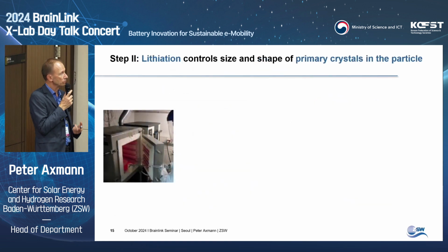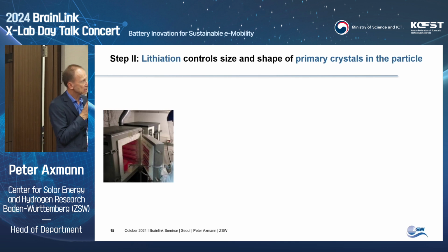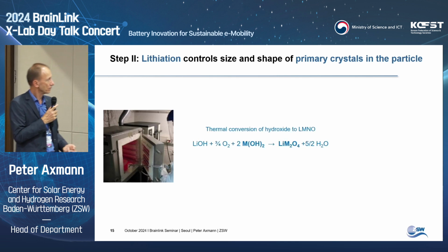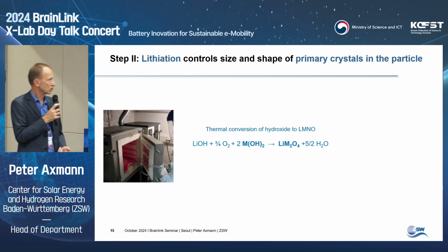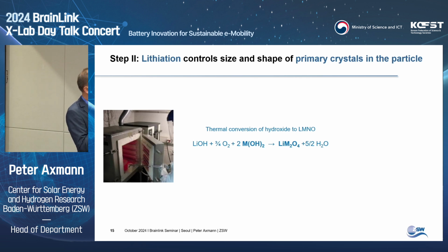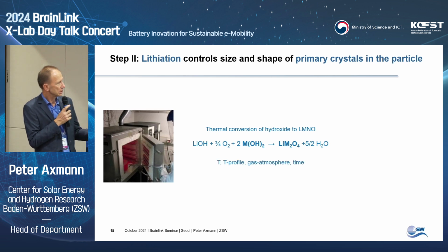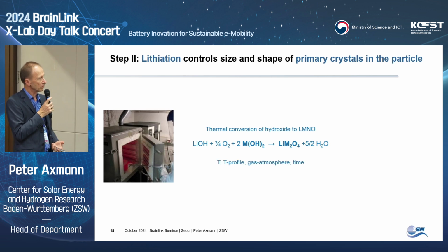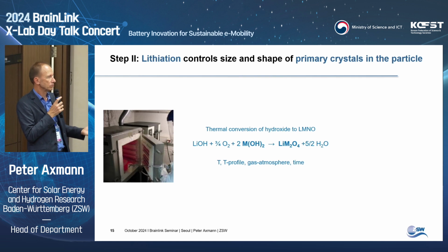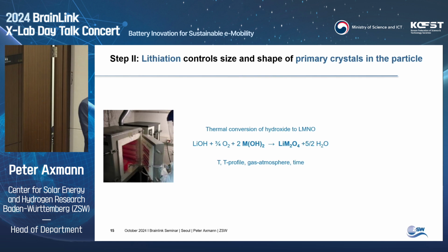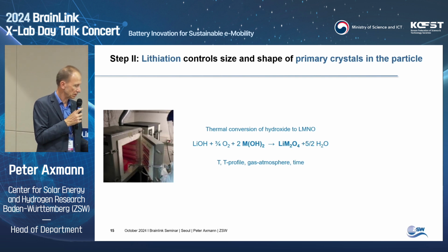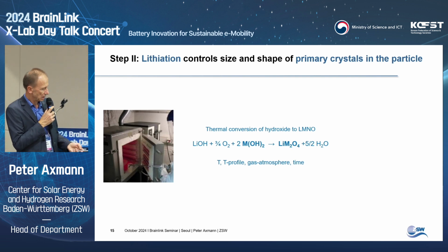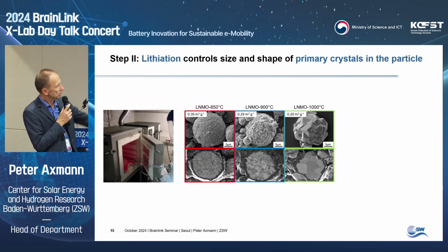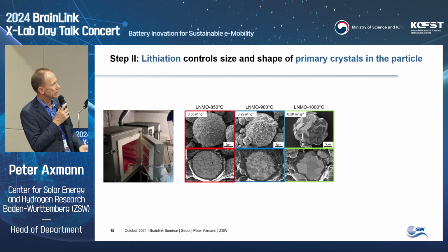Step 2, the lithiation. Here we can control size and shape of the primary crystals within these individual particles. The reaction is a thermal conversion of the hydroxide to the final product, here as well, LMNO. You put lithium hydroxide to it, oxygen, the hydroxide, and end up with a final cathode active material at 700 to 800 degrees. You can change the temperature here, temperature profile, gas atmosphere, and time of exposure. And just changing the temperature directly shows in the single particles, which came from the same precursor, that you can optimize or increase the crystal size within the particles drastically.